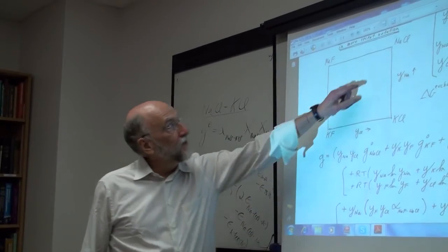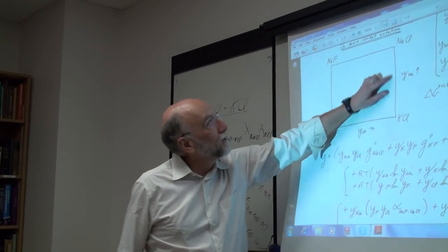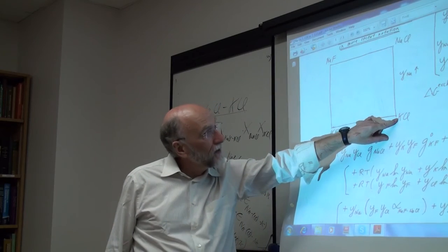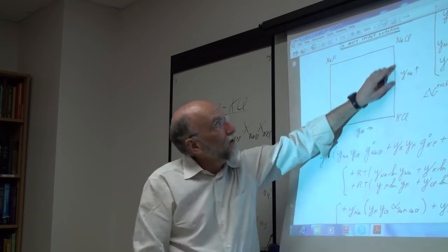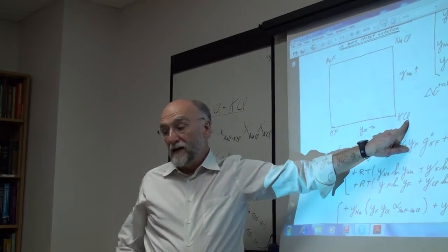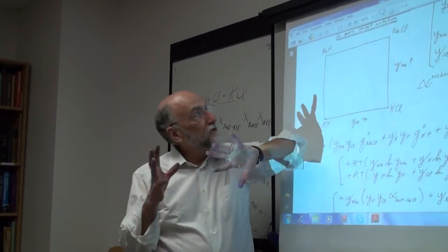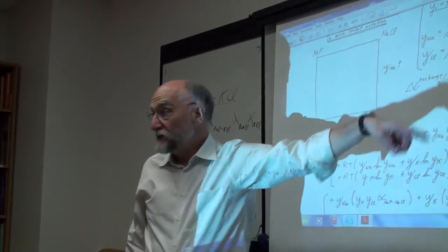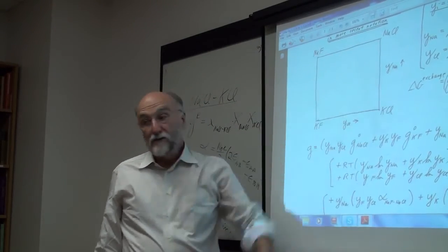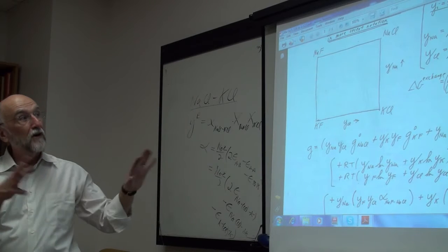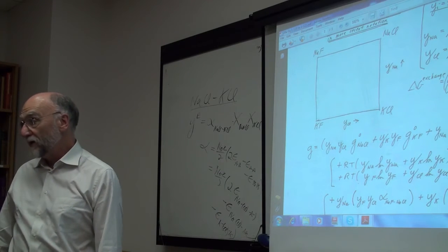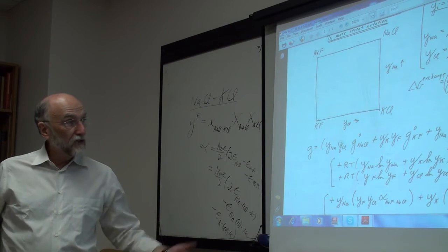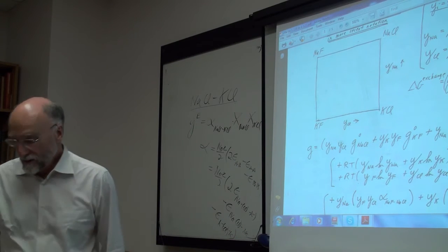So you can treat this then. This is called a common ion system, NaCl, KCl. And although this common ion system is really a sublattice model, since one sublattice is occupied entirely by chlorine, you can just forget it. And you apply a one sublattice model just like any binary system. So for the sodium chloride, potassium chloride system, you can apply everything we've talked about up till now for a one sublattice model. It's just exactly the same thing. The second sublattice is just dropped.